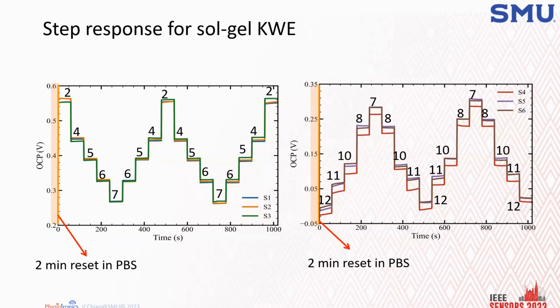This is 1 cycle, and this is the second cycle. We found out that the sol-gel device 1 to 3 was very uniform. However, device 4, one of the devices, has a slightly different performance. We did find out that the device 4 has a slight difference because when we printed, the device 4 is on the edge. So maybe the thickness was different from 5 and 6. So using this measurement, we can see that the responses are pretty repeatable after the reset.